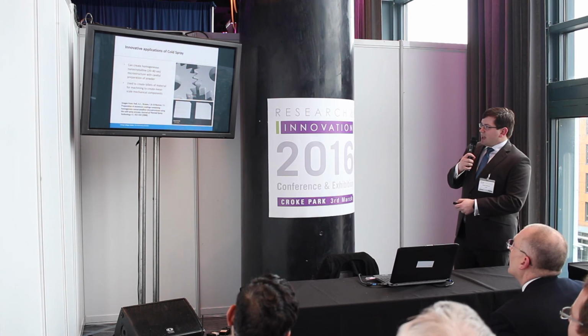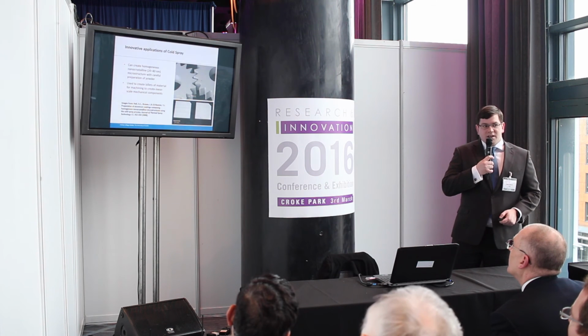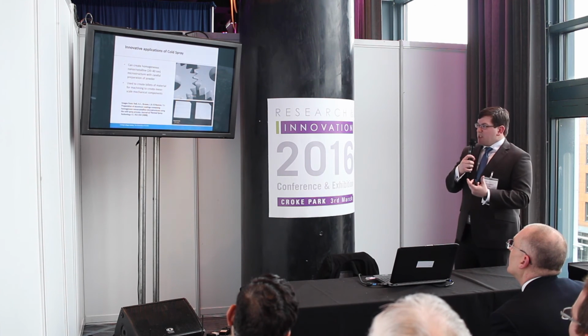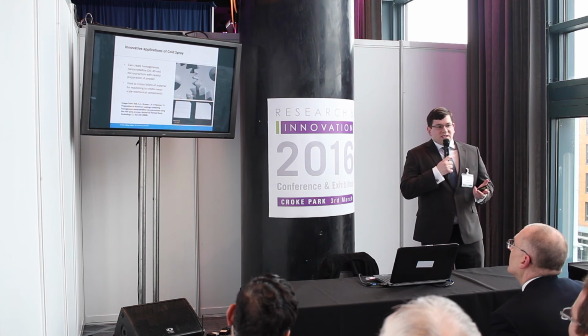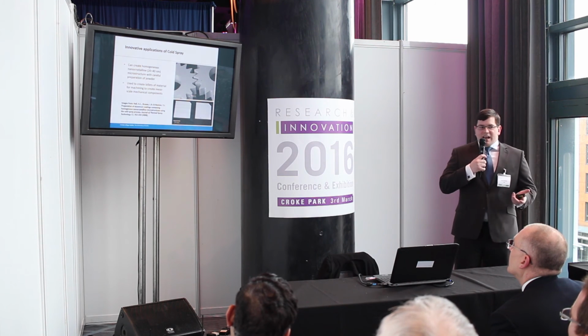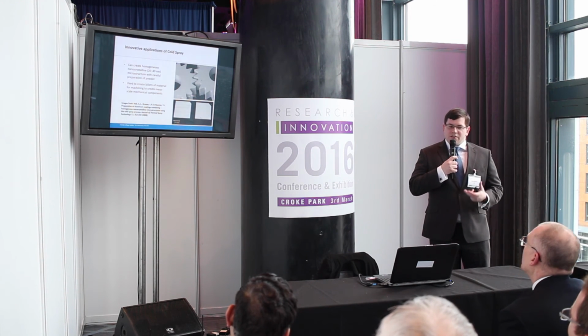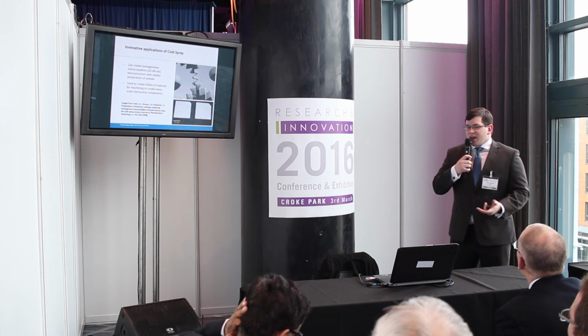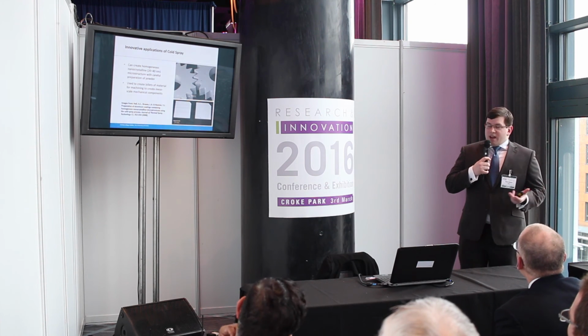You might not be able to see this scale bar, that's a 200 micron scale bar. So you're looking at gears with teeth of maybe 200 microns height. If you were to make these using conventional casting techniques, you run into a lot of issues depending on where your grain boundaries and your dislocations are. They can and will fail, so you can't really control it.